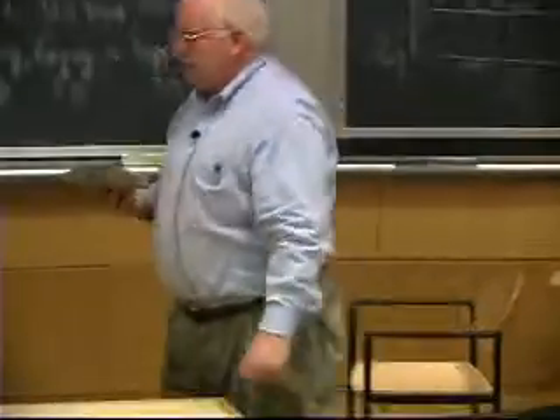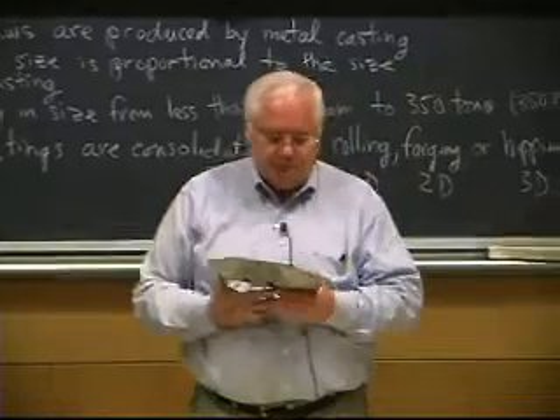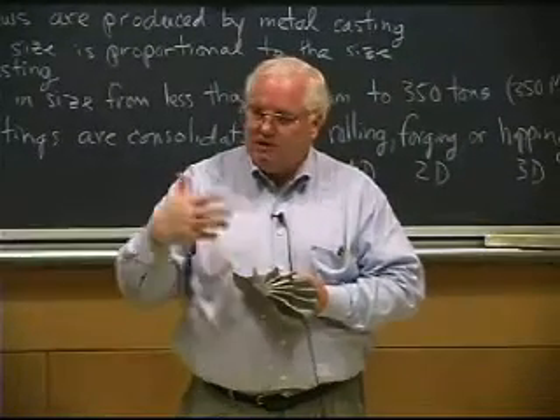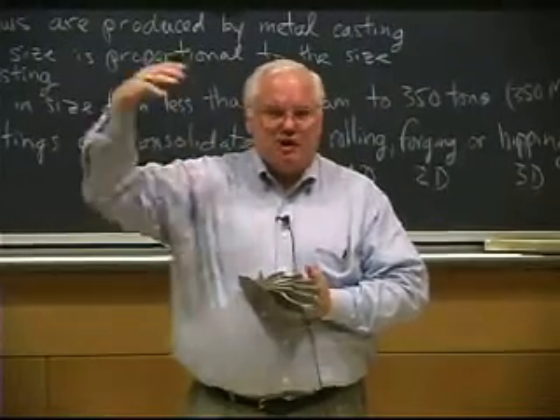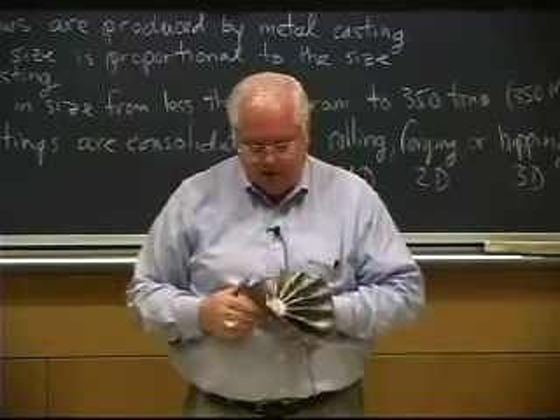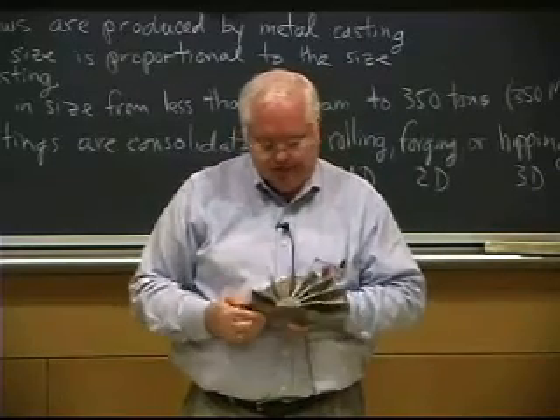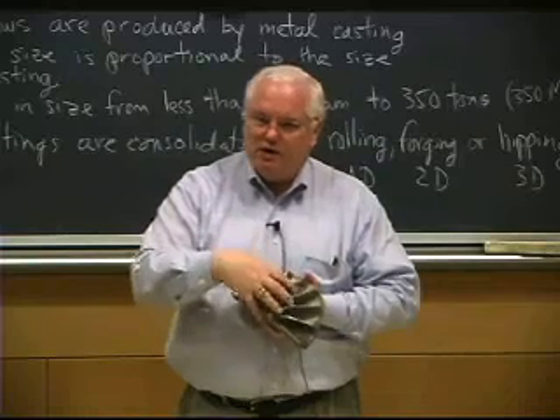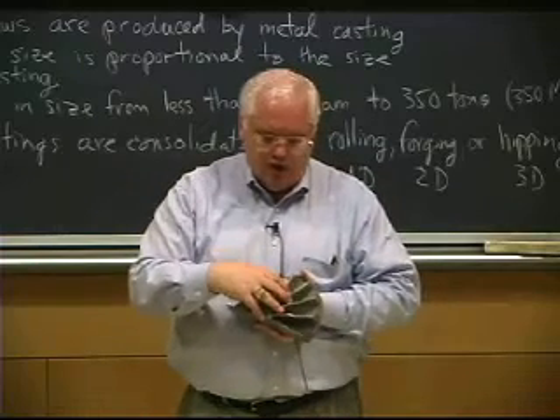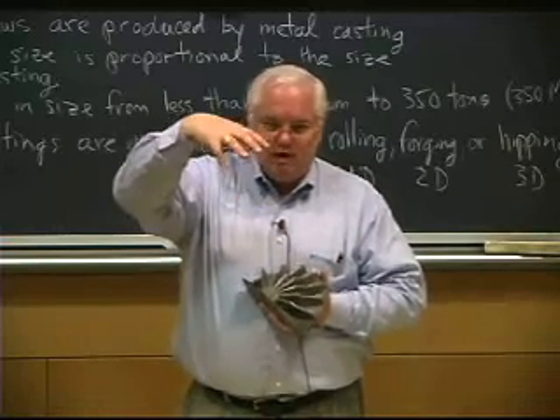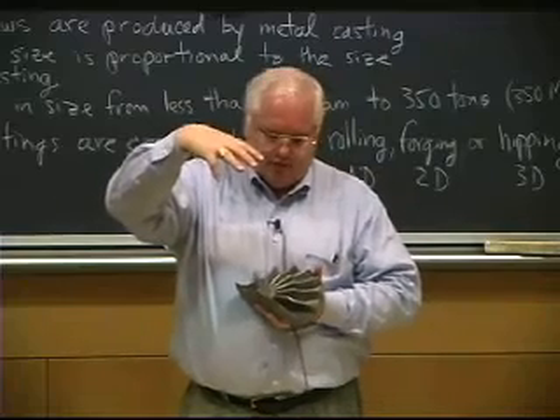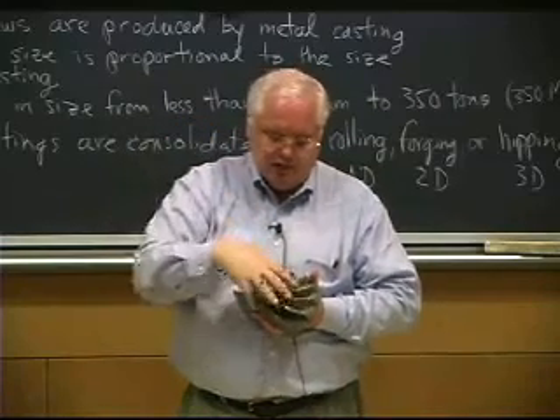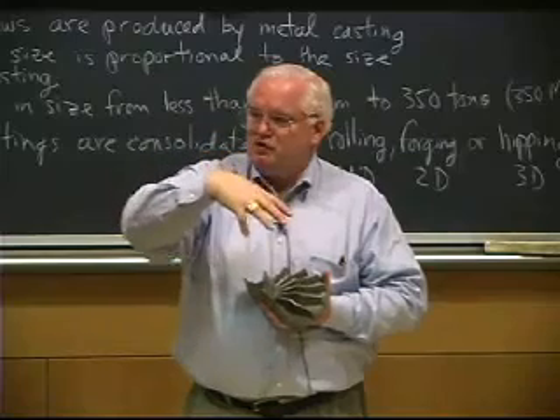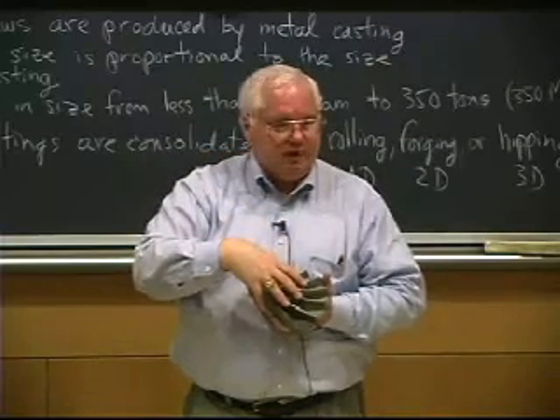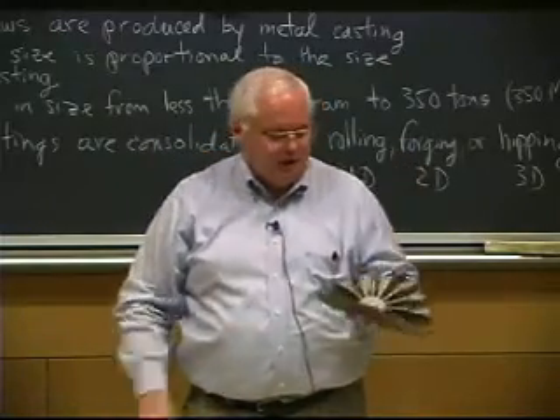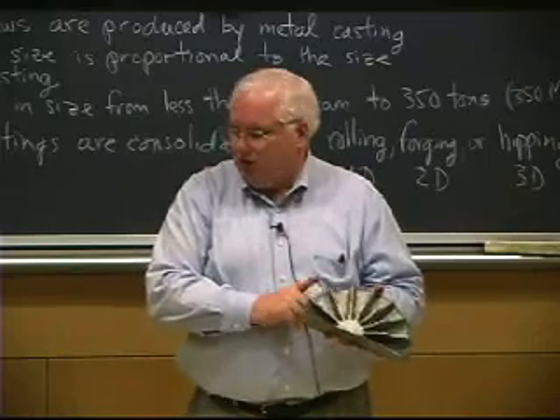For certain nickel-based alloys that are used in jet turbines, it turns out you can get very, very fine grain size, so they become super plastic. Not at room temperature, but at high temperatures. And so Pratt & Whitney in West Palm Beach, the military division, 15 or 20 years ago, developed isothermal forging of IN 100 nickel-based superalloy, where they could get very fine grain size, and they would come in with these graphite dies that would take high temperatures for a long period of time, and they just slowly squeeze the final part. Okay, and they get something that was a more complete final part than this one.